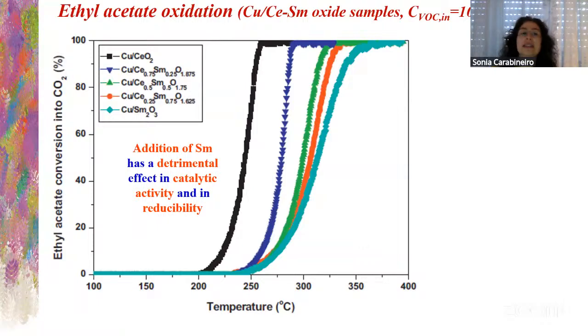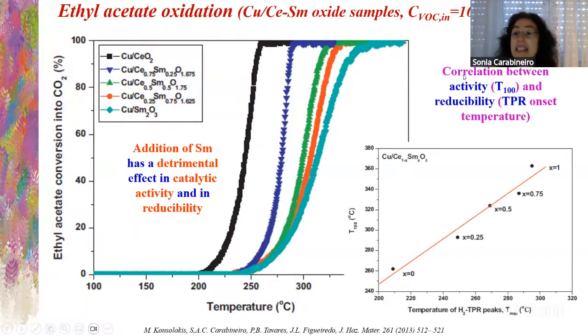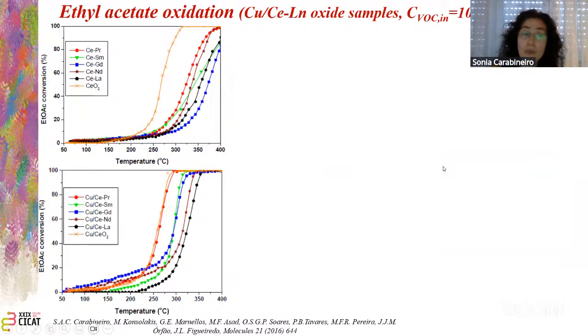Here we have copper on mixed cerium oxide samples. We added samarium to cerium oxide, and we saw that it had a detrimental effect on the catalytic activity and the reducibility. So the best sample was copper on cerium oxide. If we add samarium, it only gets worse, and with samarium is the worst of all. So you see here, there is a correlation between the activity and reducibility. So we obtained that. We also have here ethyl acetate oxidation for